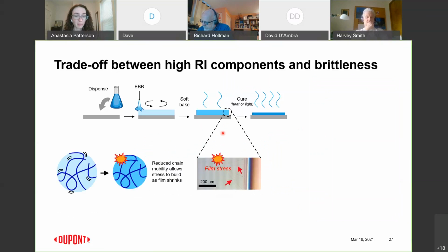And again, when we look at this film, before we even get to the cure process, there are cracks. So I've indicated a little bit the regions where cracking exists. I hope you guys can see that. But there's long cracks that cross the film in this direction as well as in this direction. And again, what we're looking at is the left part of this microscope image is the actual polymer film, and the right portion is where that film has been rinsed off at the edge of the wafer.